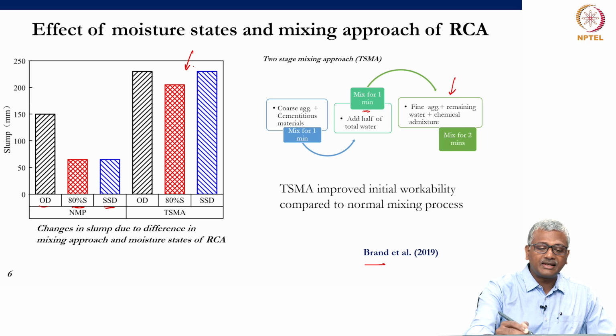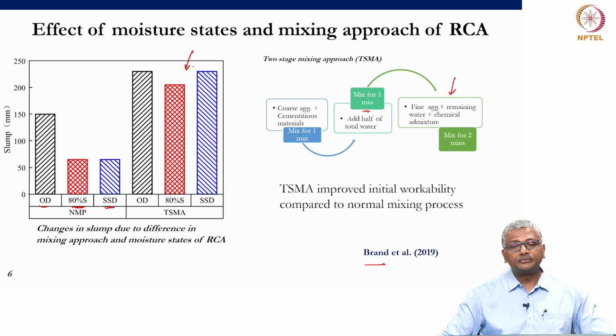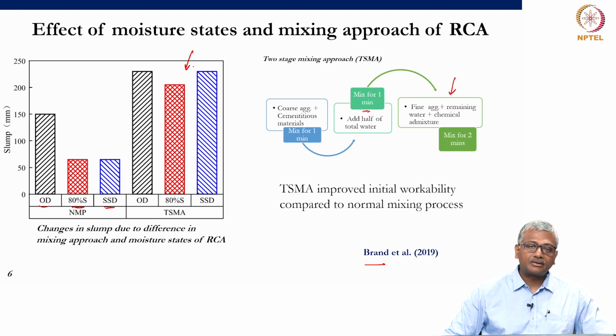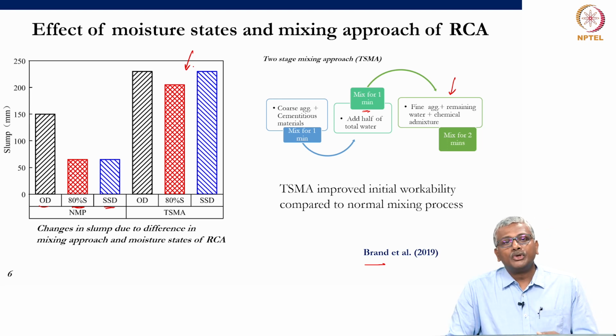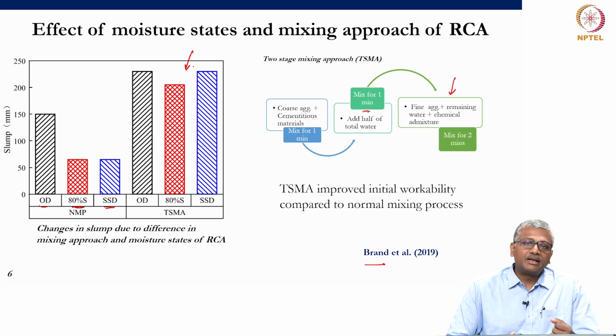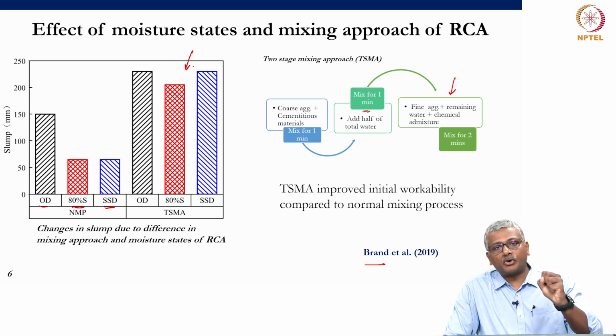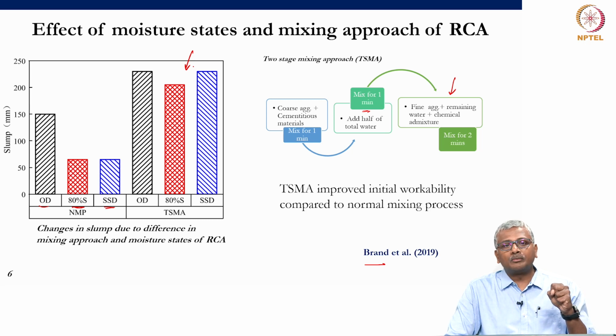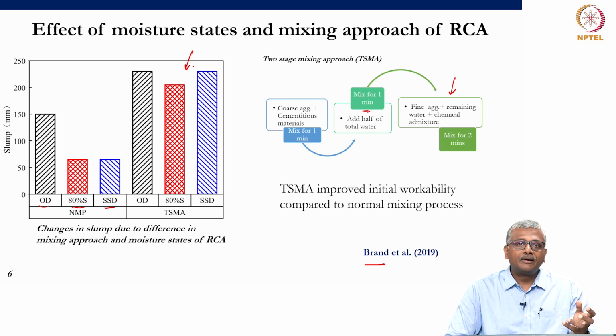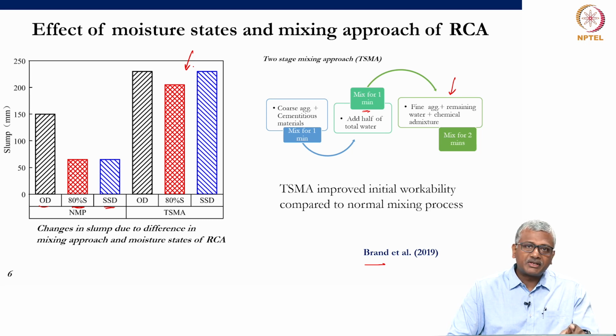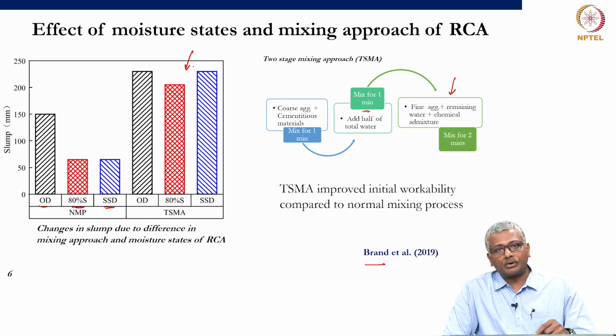What you end up doing is getting a much higher slump when you have either oven dry or saturated surface dry or even partially saturated aggregate. So, why is that happening? Obviously, because you have now satisfied the demand of the aggregate to have its pores filled up with water. So, because of the adhered mortar, this aggregate will act like a sponge and start absorbing moisture from the mixed water, right. So, again, make sure that when you do the mix design, you compensate for this additional water content. If you have not compensated, you need to then determine the effective water cement ratio of your concrete.